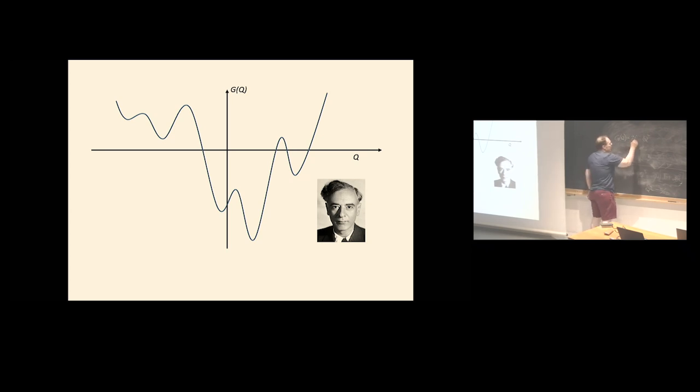And then we're going to multiply by a toggle, which allows this prefactor to change sign. So if you're above Tc, T is greater than Tc, T minus Tc is a positive number. That allows this prefactor to be positive. If you're below Tc, T minus Tc is a negative number. That allows this prefactor to change from positive to negative, exactly the behavior that we need. It might not be linear in temperature, but for the moment, we don't care.